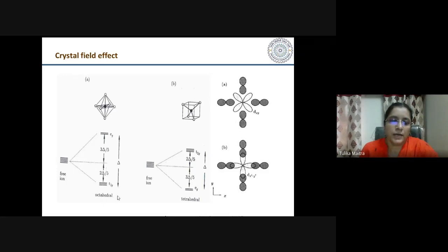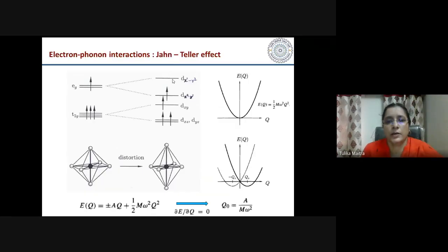So in an octahedral environment, we see that the splitting is like this, that there are triply degenerate t2g orbitals which have lower energy, and doubly degenerate eg orbitals which have higher energy, whereas in a tetrahedral environment we see that the splitting is opposite and the splitting is also less. So how much the energy difference between these two states is can be evaluated by doing density functional theory electronic structure calculations.